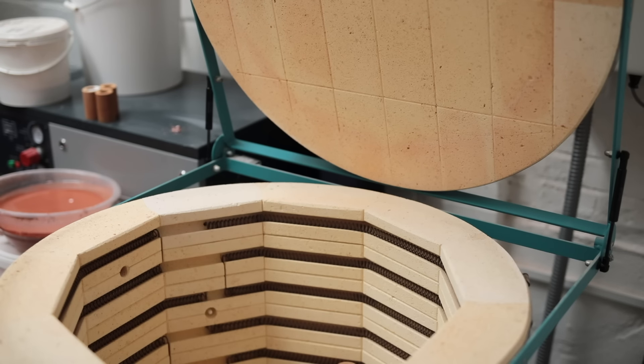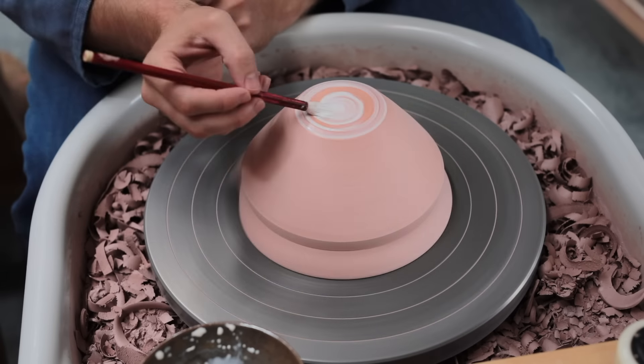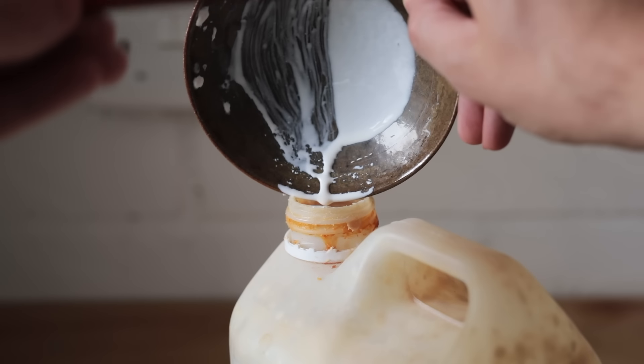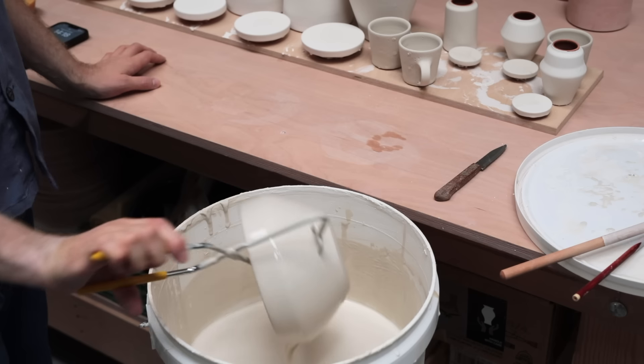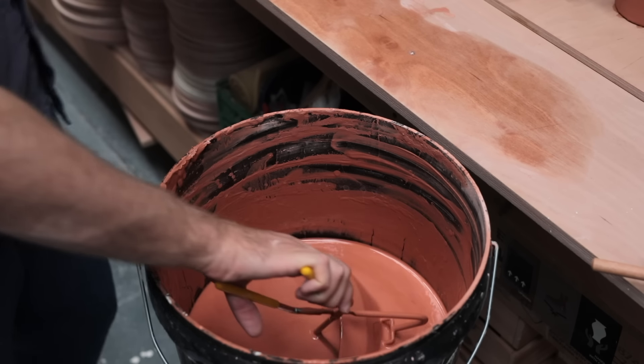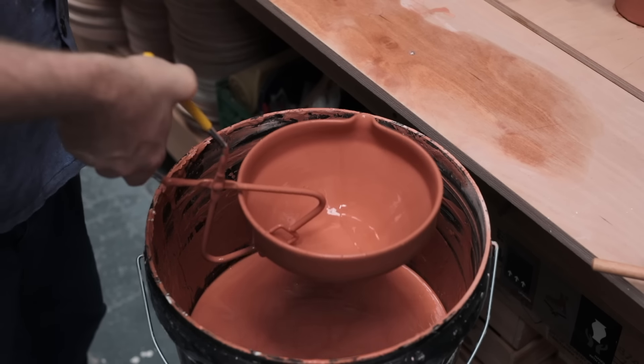It's these raw materials that make up the glaze, the water being more of an agent of transport. As I don't want the bottoms of these to be glazed, I brush a thin layer of wax emulsion over them, thus preventing the water from being absorbed into the body, meaning none of the raw materials can stick to the clay. You can actually glaze the bottoms of pots, but it requires firing them in a different way, as if I glaze the bottoms and then place them directly on the kiln shelf, the glaze would turn into molten glass during the firing, fusing the pot to the shelf. So you need to create a barrier between the two, such as wadding or some kiln stilts. As for the wax emulsion itself, it just burns away during the firing, and you would never even know it was there.